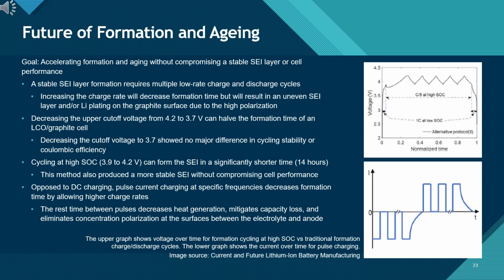Future of formation and aging. This slide highlights emerging approaches to shorten formation and aging while preserving SEI stability and long-term cell performance. Traditional formation relies on multiple low-rate charge/discharge cycles to build a uniform SEI. However, increasing the charge rate too aggressively can lead to uneven SEI growth or lithium plating due to high polarization.